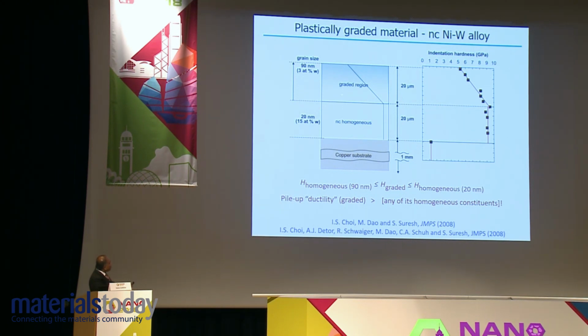So we create a surface layer, and this is using some material that we produced at MIT in collaboration with Chris Schuh. We have a surface layer that's about 20 micrometers thick, and it's a nickel tungsten nanocrystalline alloy. It has a grain size of about 90 nanometers. And then you have a small homogeneous layer of nanocrystalline material, and then you have a copper substrate. And then we do the indentation work.